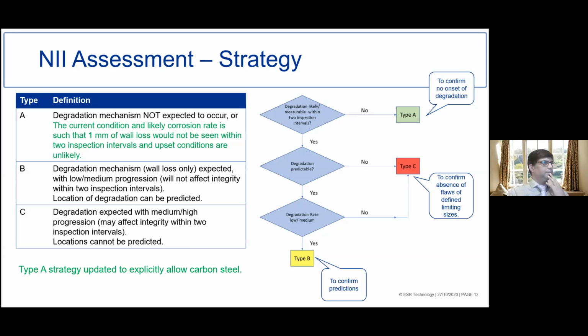And type A. So type A was originally intended for vessels that are corrosion-resistant alloys, or clad internally with a corrosion-resistant alloy. So the idea was it's very much to confirm there's no onset of degradation. But we've now explicitly allowed carbon steel vessels, but the proviso there is that they really do have to have a very good history of no corrosion at all. And it is very unlikely you would see corrosion. So it is more along the lines of dry gas processing vessels.